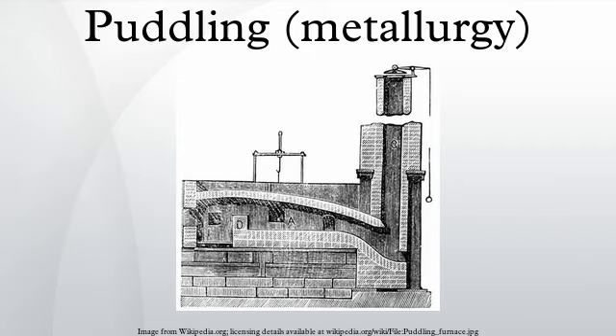One big problem with puddling was that almost 50% of the iron was drawn off with the slag because sand was used for the bed. Hall substituted roasted tap cinder for the bed, which cut this waste to 8%, declining to 5% by the end of the century. Hall subsequently became a partner in establishing the Bloomfield Iron Works at Tipton in 1830, the firm becoming Bradley, Barrows and Hall from 1834.